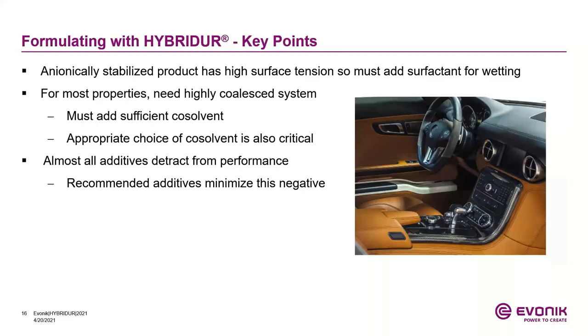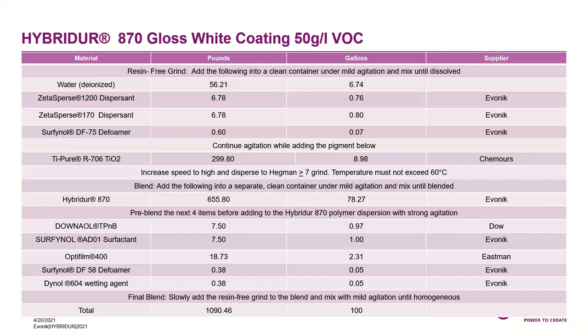Formulating with Hybridurs, here is an example of a gloss white coating of 50 grams per liter VOC. Formulating with Hybridurs is fairly easy. We typically do a resin-free grind. And in the resin-free grind, it's basically a pigment dispersion like ZetaSperse 1200 and the combination of the ZetaSperse 170 and a defoamer and water, and TiO2 is dispersed to a Hegman grind of 7, the temperature not to exceed about 60 degrees centigrade.